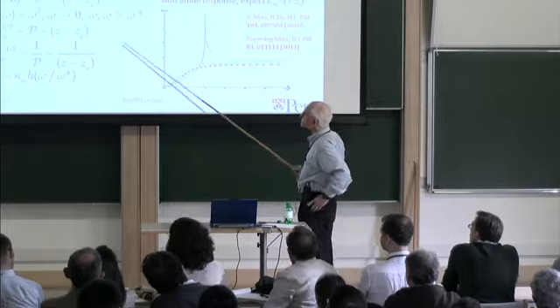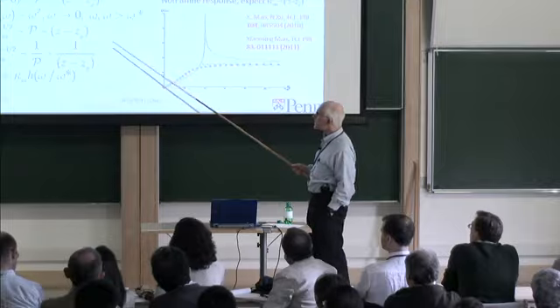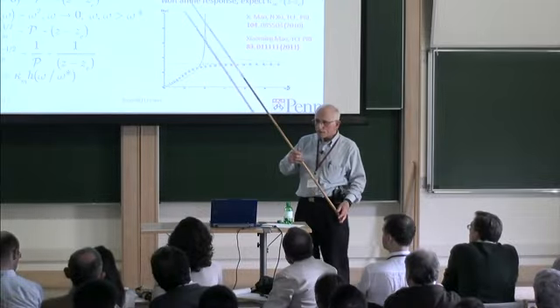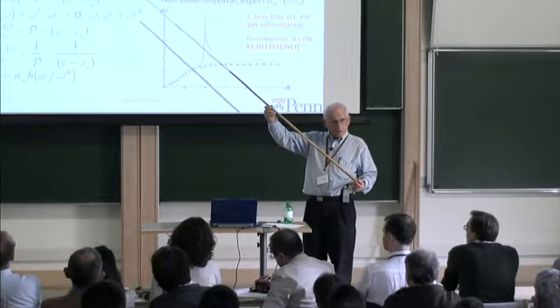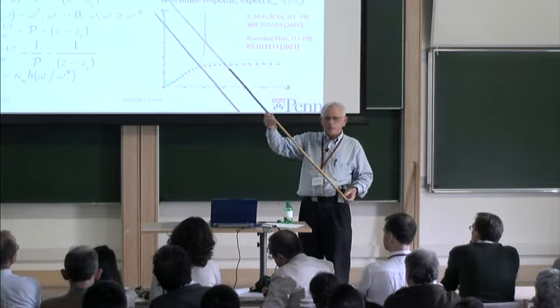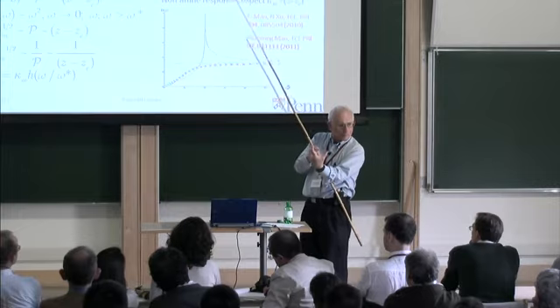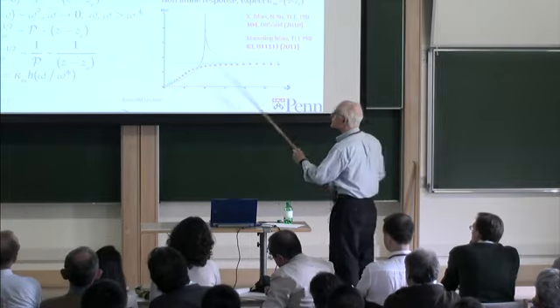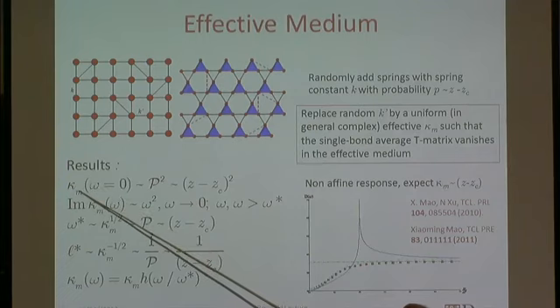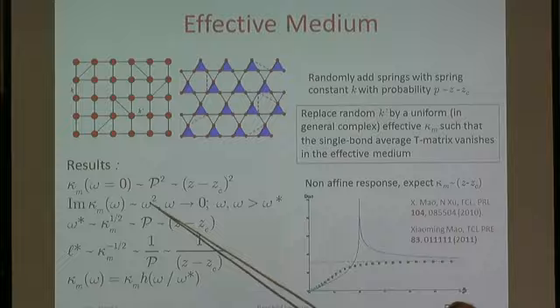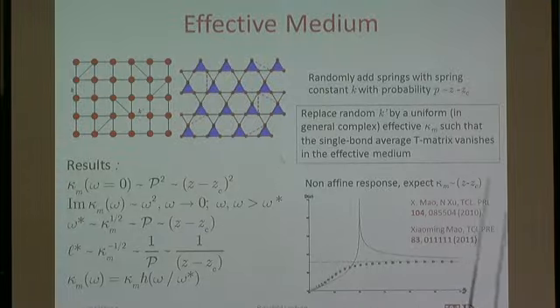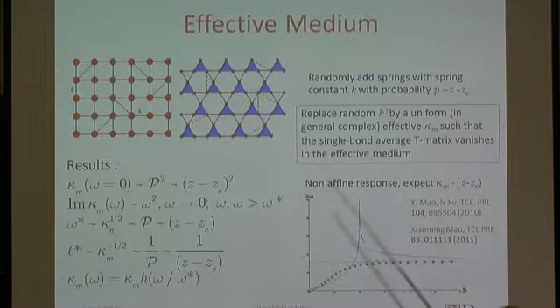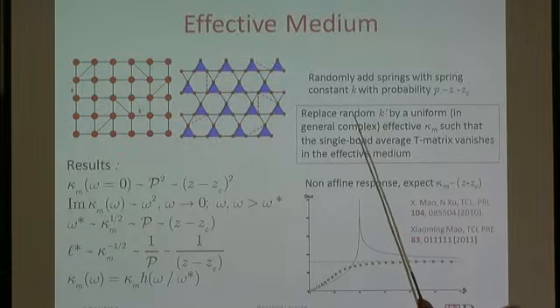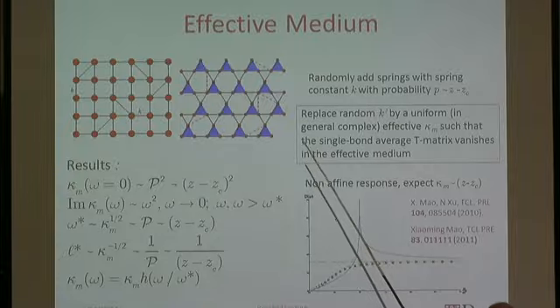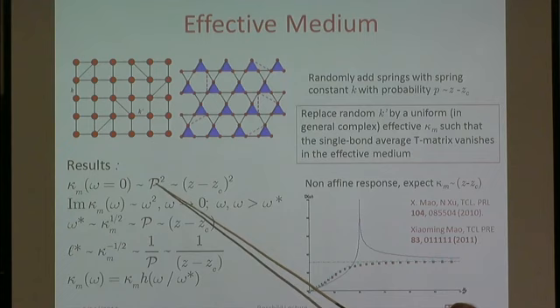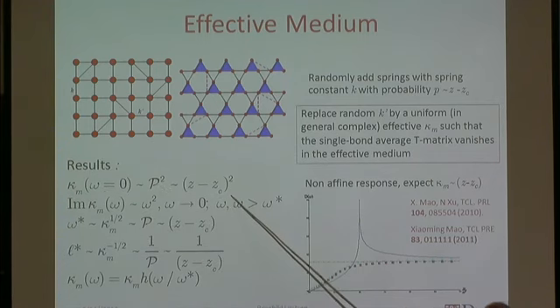And there's a well-defined approximation that really works very well called the effective medium theory, or the CPA, depending on where you're coming from. Basically, you look at each bond, and you replace it by an effective bond such that the scattering from a random bond is 0 in the effective medium. And when you do that, you find that the effective next nearest neighbor spring constant at 0 frequency scales not as the probability, which you might have expected. You would have thought if you're doing an average thing and you just put things down at random, that the average spring constant would just be the probability that's there times its strength. But no, the calculation gives p squared, which gives that this k goes as z minus zc squared.